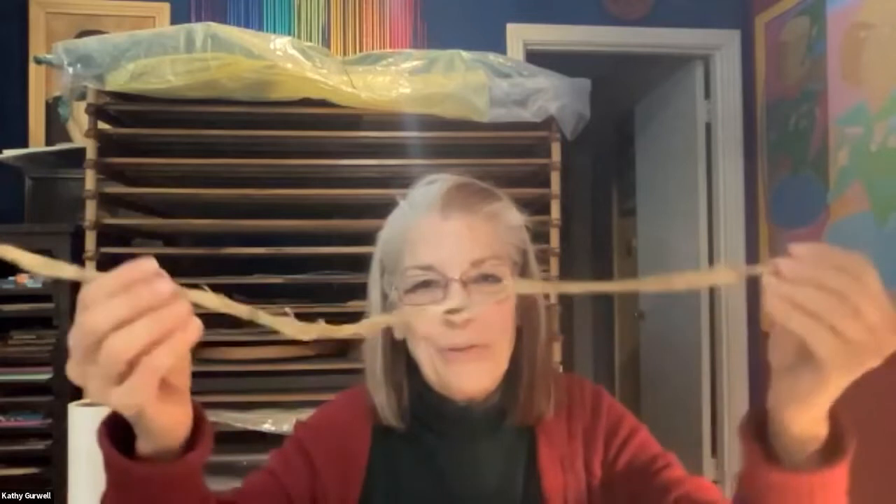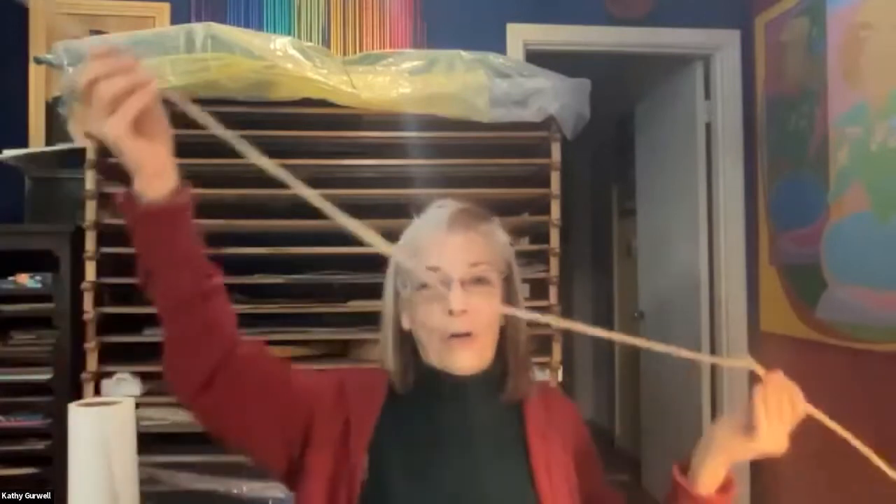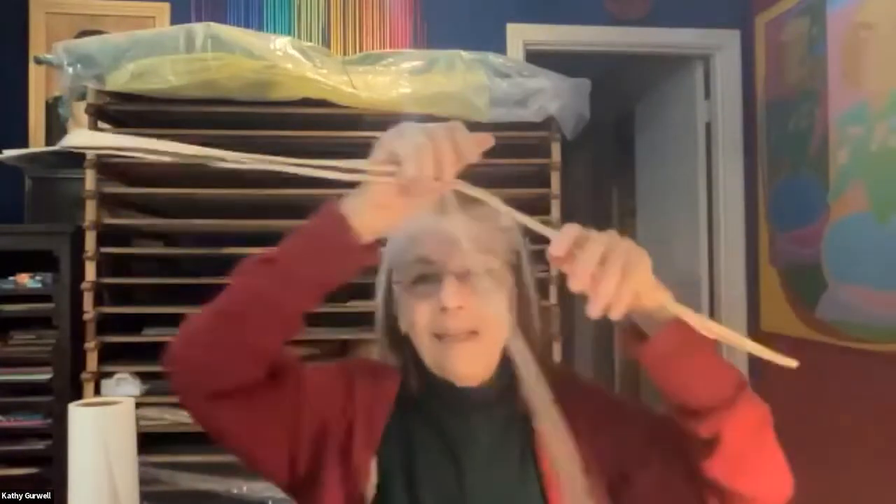Here's amate — we're probably all familiar with Mexican amate, which is what people use to do wonderful colorful paintings on in Mexico. It's a bark that's been beaten into itself. And then kozo mulberry — this is the dry kozo. This is a branch that's been steamed and stripped, showing the dried white inner pith of the branch. Here's even a larger branch, folded up, to show how very long these branches of the plant are. It needs to be boiled further for several hours with soda ash or wood ash, and then it can be beaten — I hand-beat it, though people do use machine beaters.